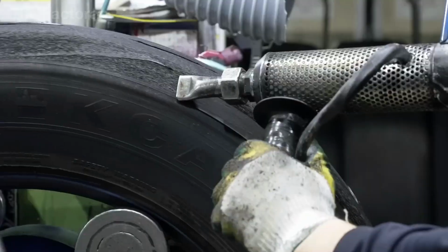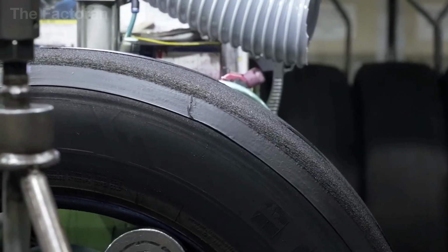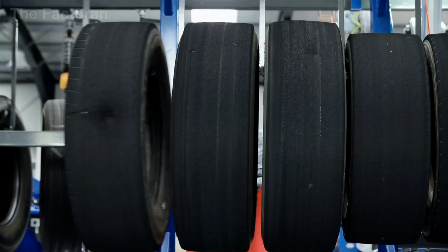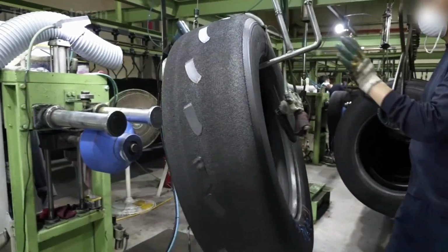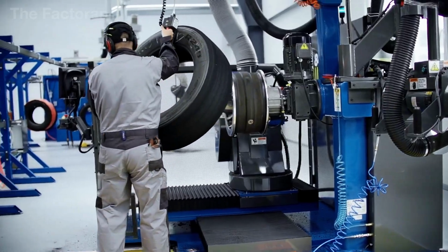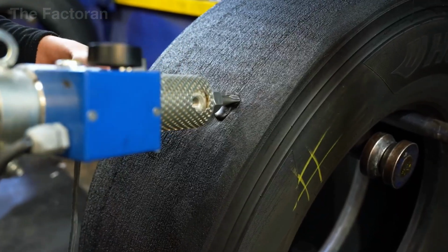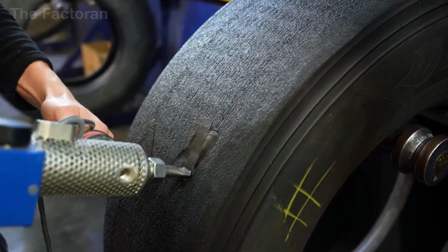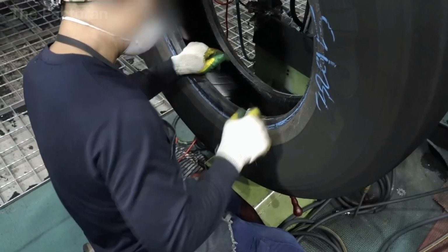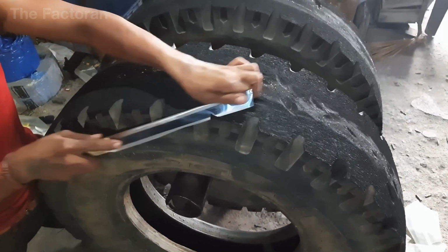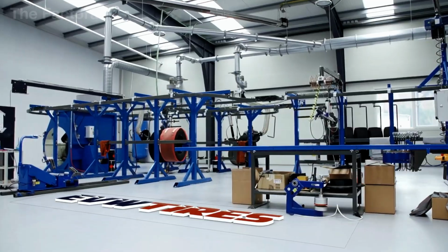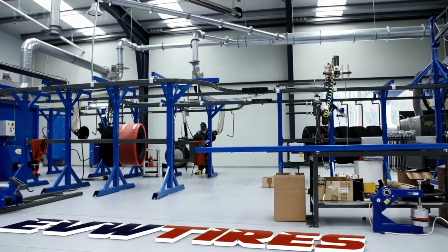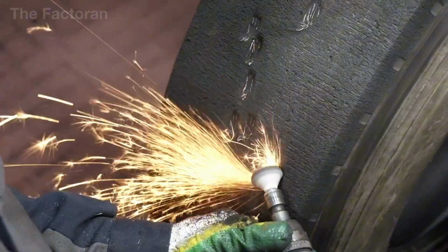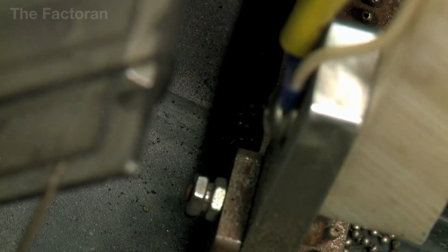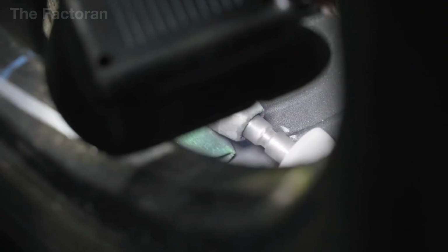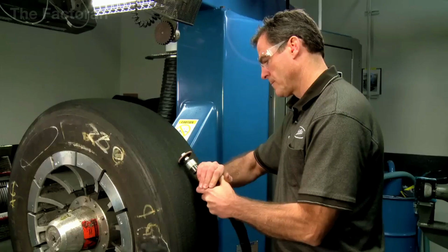Once the repair is complete, the surface is buffed again to make sure it blends seamlessly with the rest of the casing and doesn't leave behind a weak spot when the tire is back in service. What matters most is that every repaired point has elasticity and adhesion almost identical to the original rubber. Some advanced facilities even scan the casing electronically or take X-ray images after the repair to make sure no hidden defects remain. Thanks to this process, a single casing can be retreaded two or three times and still be safe, saving up to 70% of the raw material compared to making a brand new tire.